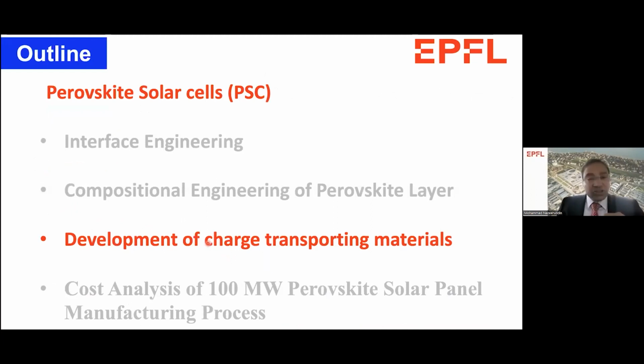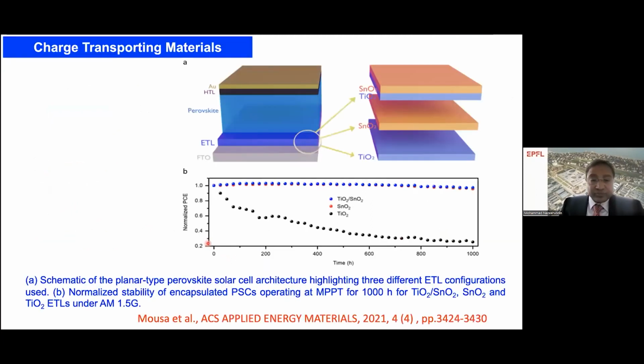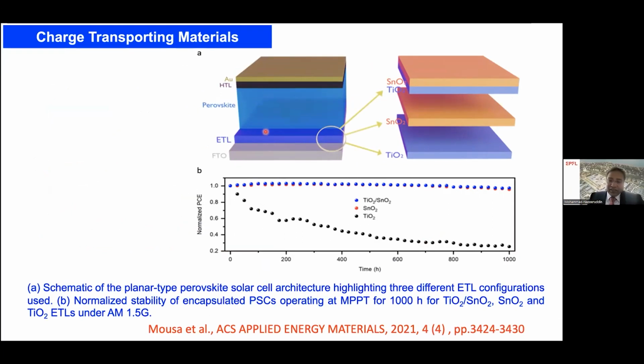Now I turn my attention towards the development of charge transport materials. As we know, we have 2 main charge transport layers, the electron transport layer and the hole transport layer. These 2 are the weakest links in the perovskite solar cell, besides the perovskite. So what is the weakest link? When we use pure TiO2 as the electron transport layer, you see the efficiency over a long time period, 1000 hours, is decreasing significantly.